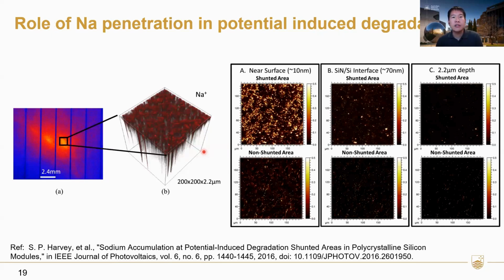Next, it's also been used to study a well-known degradation for PV panels in operation in PV farms called potential induced degradation. This is when solar panels are connected in series, resulting in voltages of a few thousand volts relative to the ground. This high voltage induces the diffusion, the migration, of charged ions such as sodium. When they compared the sodium concentration in shunted and non-shunted areas, they found that the shunted areas show significantly higher concentration of sodium.